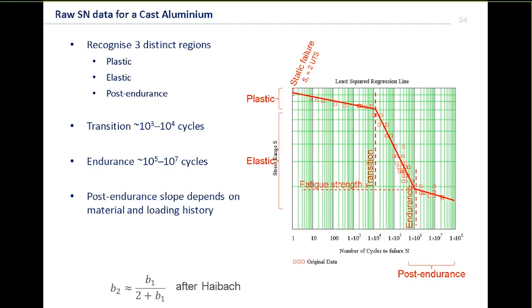Beyond the endurance limit, the post-endurance region has a different slope, and we can test that using high cycle or vibroacoustic testing. But in general, a lot of people aren't particularly worried about that life and characterizing it, so there are also correction factors we can apply too. So either it can be infinite life, it can carry on the same gradient, which is conservative, or after Haibach, for instance, there is a correction factor where you can estimate that if you've not gone to the expense of measuring it.